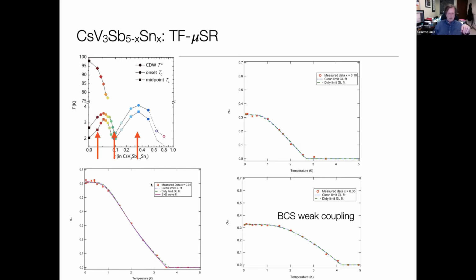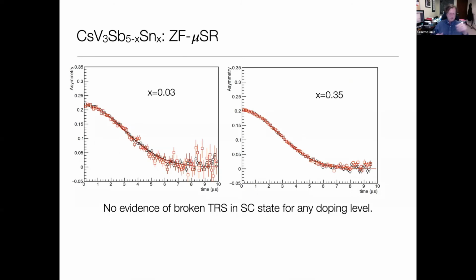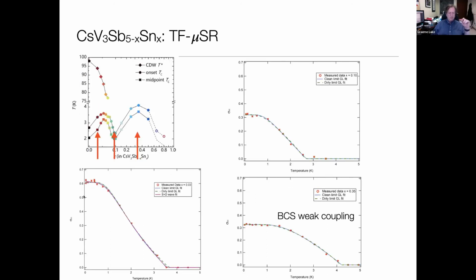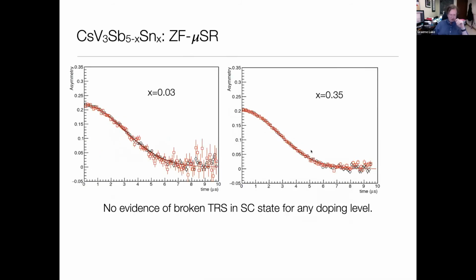Just for completeness, we've looked for broken time reversal symmetry in all of these samples. One possibility here, of course, is that you have these different domes of superconductivity. There's nothing to say that the superconducting state out here has to be anywhere near the same superconducting state as over here. There are systems where you go from being an S-wave superconductor and you change some parameter and you go into a D-wave or a P-wave superconductor. We start off with a multi-gap system and we end up with a pure S-wave BCS-like superconductor over here. And none of these superconductors have broken time reversal symmetry associated with the superconducting state.